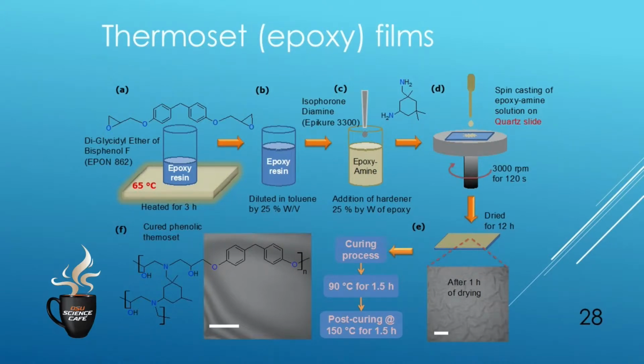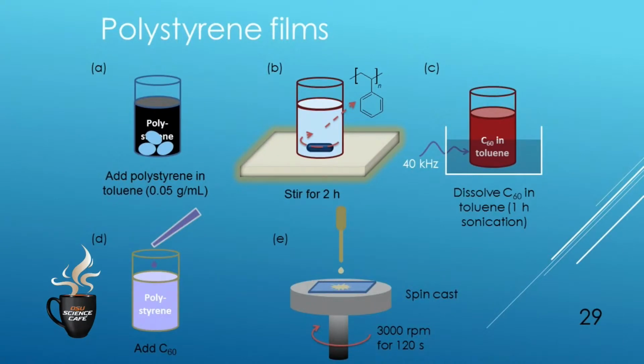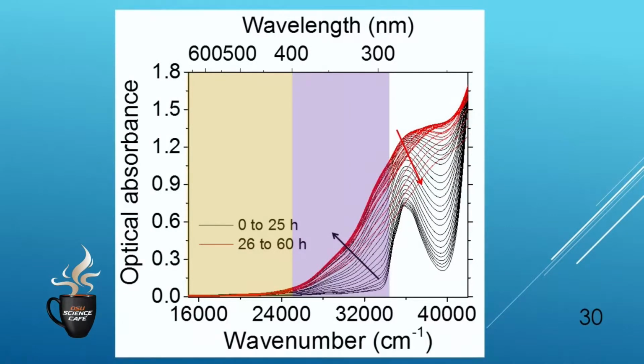That was our hypothesis. So to test this hypothesis, we made thin films of epoxy as well as polystyrene. Basically, we were putting the liquid precursor and spinning on a slide and making thin films like 600 nanometers, 700 nanometers thick. And then we were putting the samples under UVA light and checking how the optical absorption was changing.